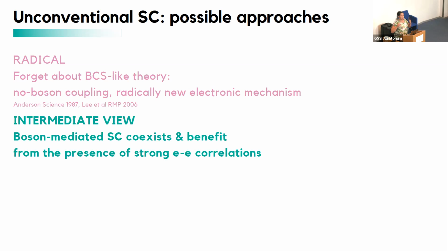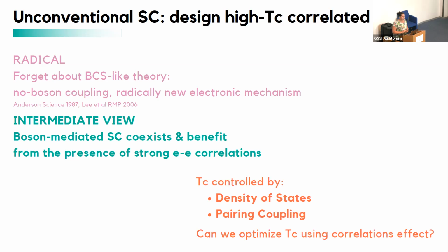I believe that there is some mechanism for superconductivity that could be, for example, spin fluctuation, maybe combined with some electron-phonon. It is not important at the moment. But what I want to see is whether these actors playing in a correlated environment are happier or not. I want to see if the correlation is actually helping and is beneficial for superconductivity. In that respect, the strategy to optimize a superconductor is going to be the same. I want to see the impact of electronic correlation on the density of states close to the Fermi level and on the pairing coupling, and see if I can enhance this aspect by playing with correlation.